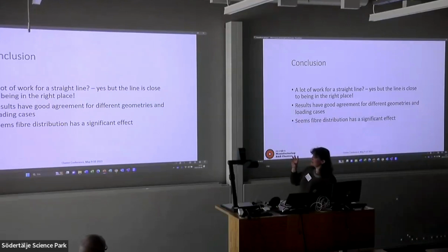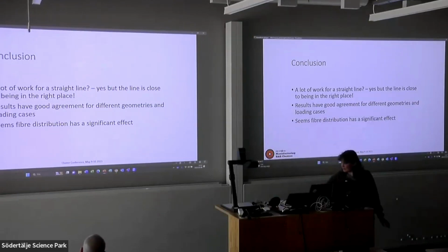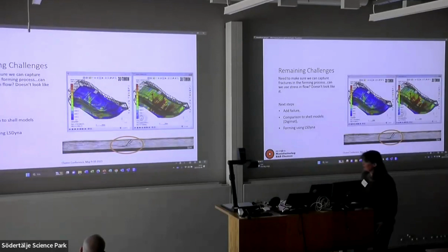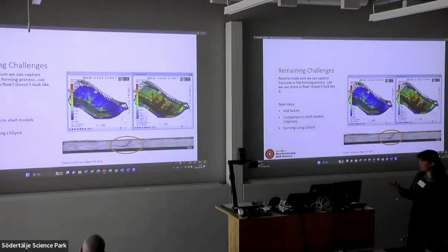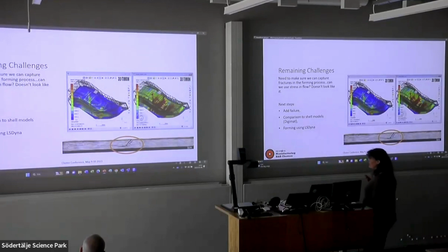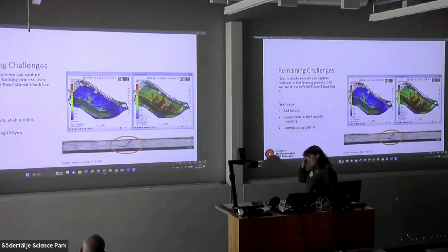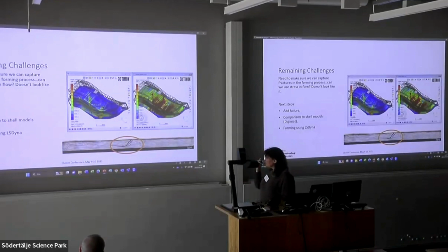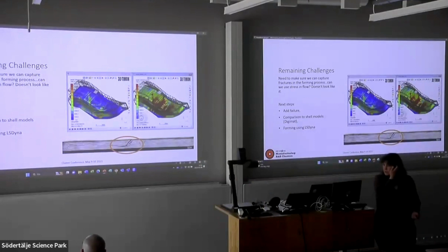The other thing we can see is that if we allow 65% versus 50%, the fiber distribution really has a significant effect on the results. Which is kind of what you expect, but I think it has more of an effect than the orientation itself. Remaining challenges. Well, I think we need to capture these fractures that are going on in the forming process. I was hoping that this would be something to do with the stress that you can capture in the flow models, but that's not the case. So I don't think the flow models are good enough for capturing those issues.